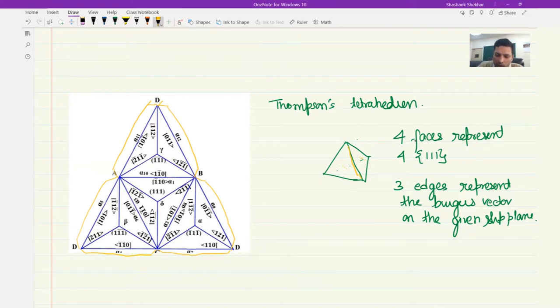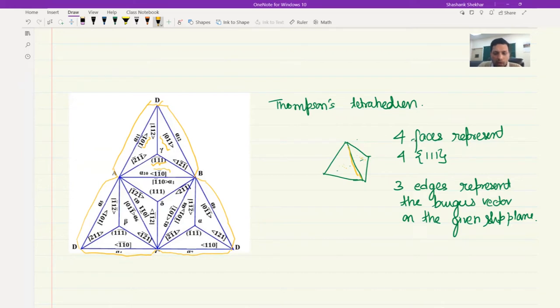Let's look at some examples. This is the (bar1, bar1, 1) plane, and the possible Burgers vectors are: a/2 [011], a/2 [1, 1bar, 0], and a/2 [1, 0, 1]. You can verify that the dot product of these with the plane normal comes out to zero, confirming these Burgers vectors lie on this plane. As mentioned, any of these Burgers vectors will lie on exactly two slip planes.